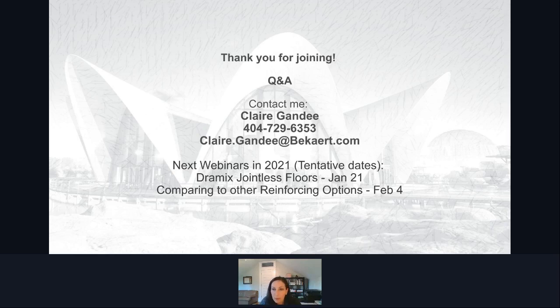All right. Is there a minimum F prime C compressive strength for the concrete, each of the fibers, or is it dependent on the aspect ratio? Yeah, so really the only minimum that we say is with the 5D fibers to use at least 4,000 PSI concrete. It works even better with higher strength concrete. That's really the only one. You can use 3D or 4D fibers with 3,000, 3,500. That works fine. Most of the testing that we have is for either 3,000 or 4,000 PSI with those fibers.